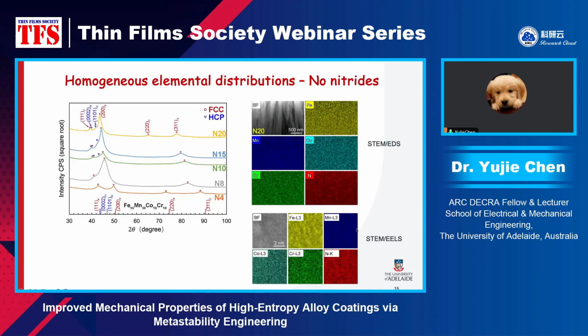But to confirm the solid solution nature, we have performed XRD, EDS mapping. This EDS mapping at microscale, and also EELS mapping at nanoscale. All these results, the EDS and the EELS, were performed at the N20 sample, the sample with the highest nitrogen content. If this one doesn't show any nitride, all the others should be solid solution phase.